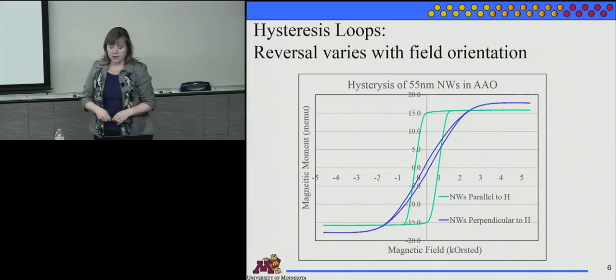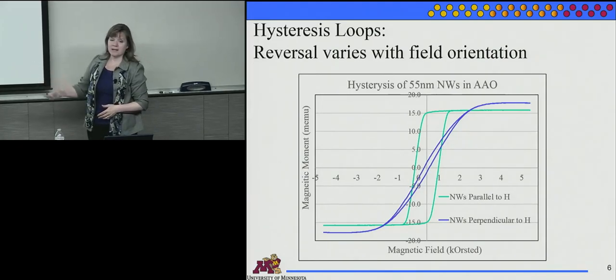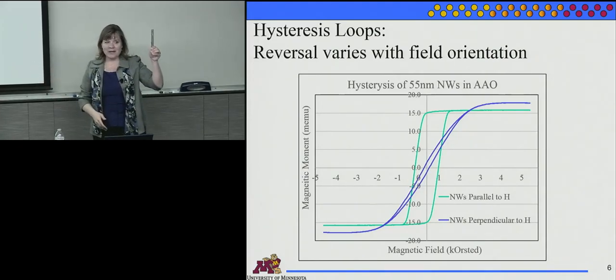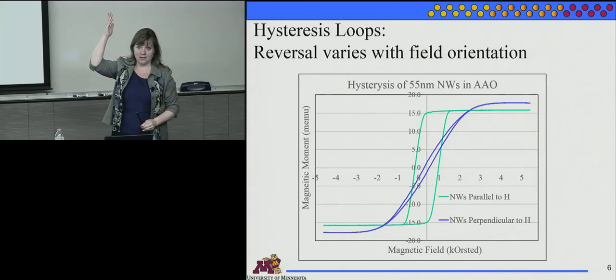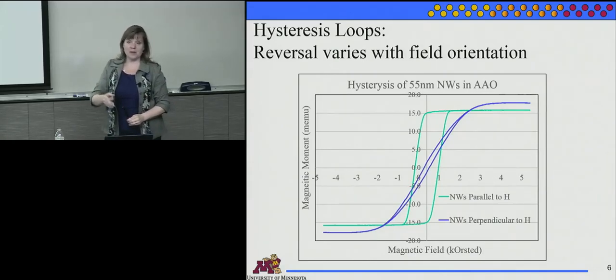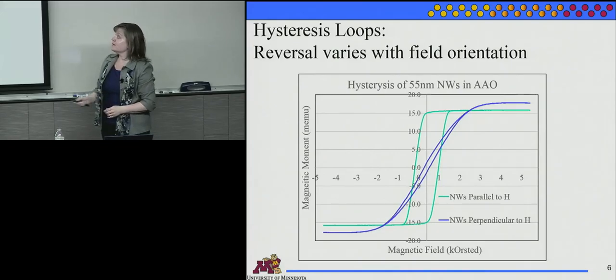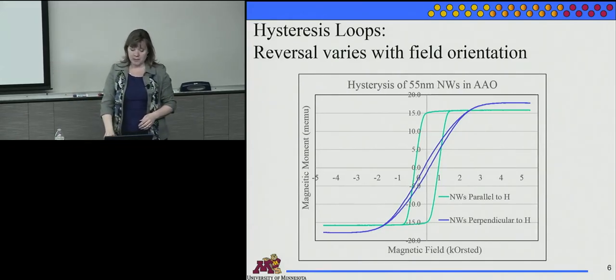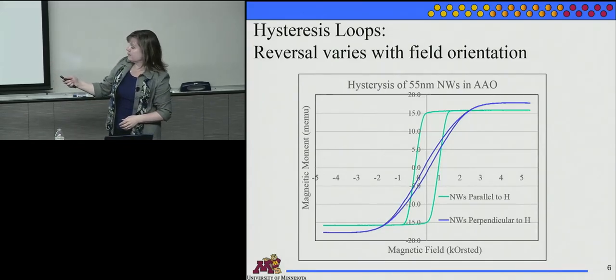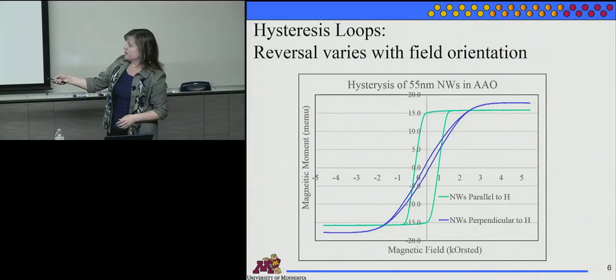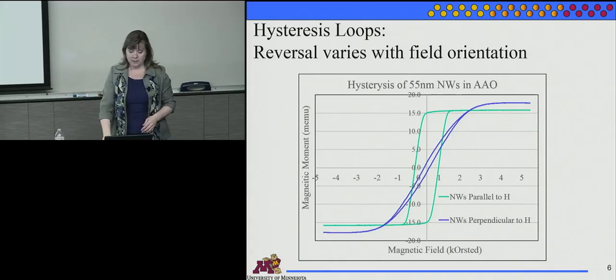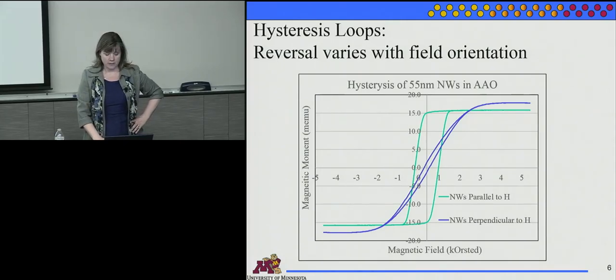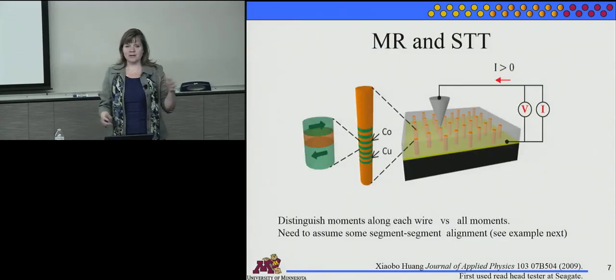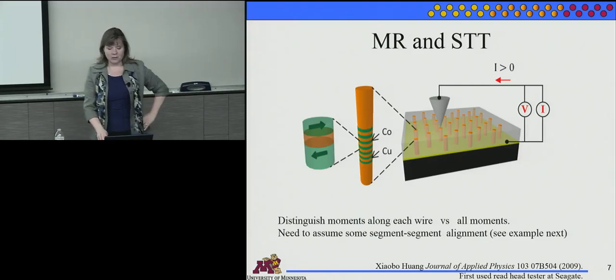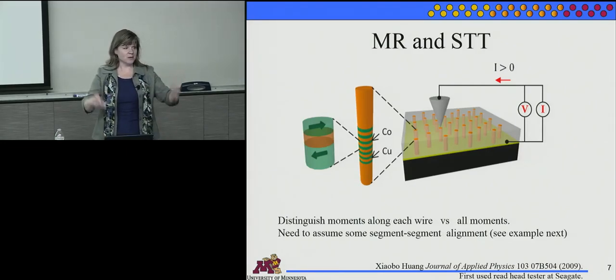And just to show, you've seen several of these also, shape anisotropy, imagine a nanowire. They can be 10,000 times longer than they are in diameter because the way we grow them, it's not a lithography process. So we can end up with pretty high shape anisotropies. Here you're seeing, depending which way you apply the field, parallel to the wire or perpendicular, you can have different shapes to the hysteresis loops. And those two aren't corrected for anything, so there's a little variation where you might not expect it, but I just want to show you the loops.